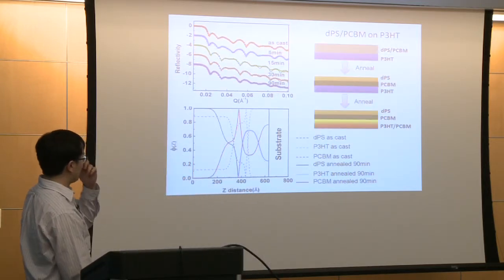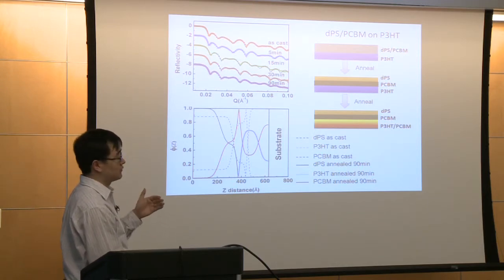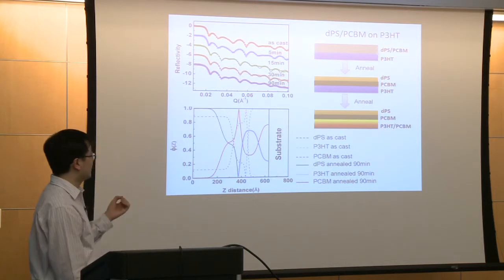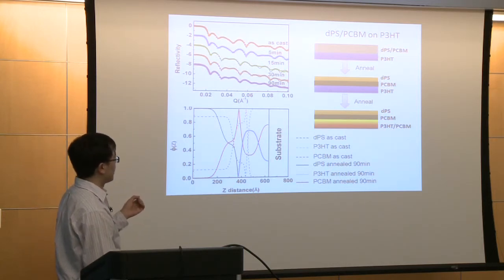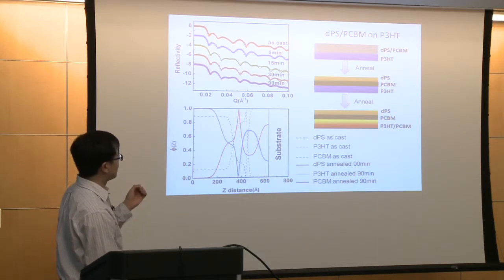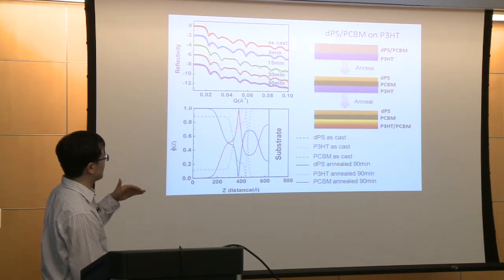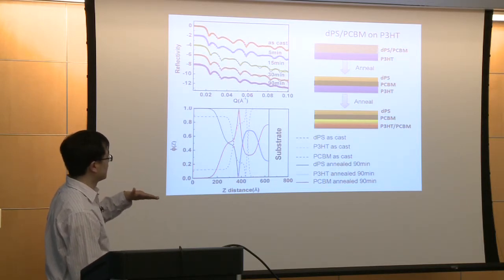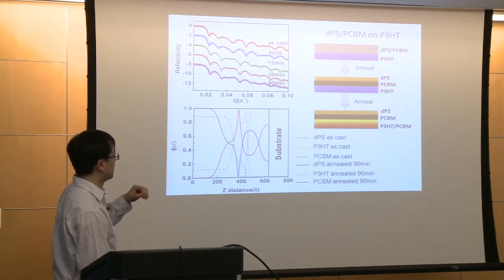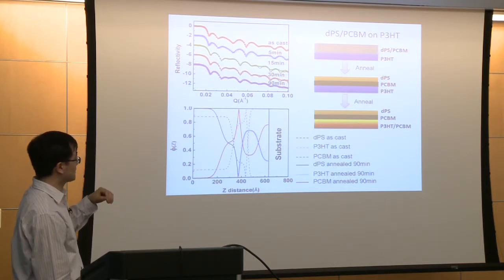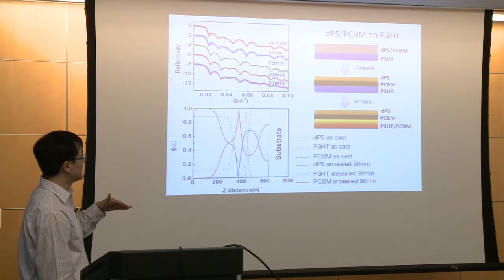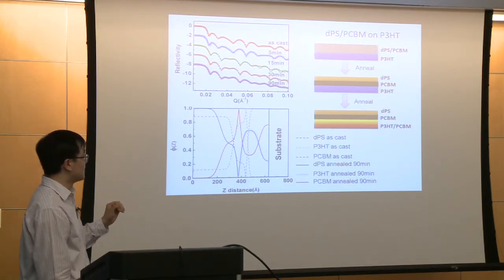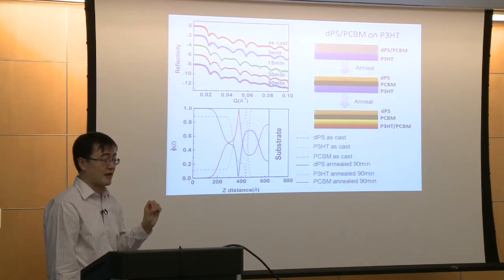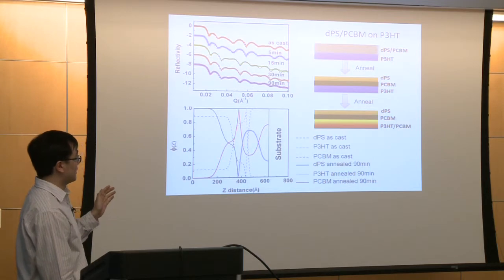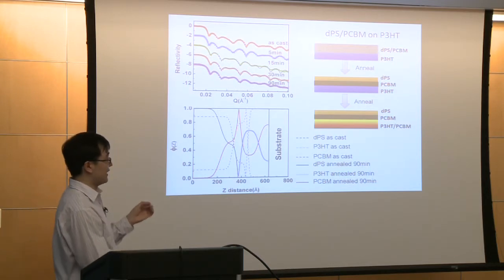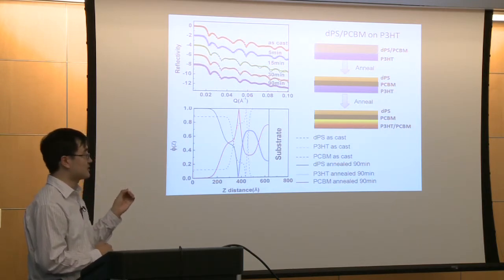Okay, so this is our second sample. In this case, we have the blend film of deuterated polystyrene and PCBM as the top layer, and we use P3HT as the bottom layer. After a certain time of annealing, we observed that most of the PCBM in the blend film goes to the interface between the polystyrene and the P3HT. If we continue annealing, some of the PCBM goes into the P3HT phase, but no PCBM goes back to the deuterated polystyrene phase. So this proves that there is repulsive interaction between the PCBM and the polystyrene. And if you remember, it is the key factor that lets us segregate the PCBM at the interface of polystyrene and the P3HT.